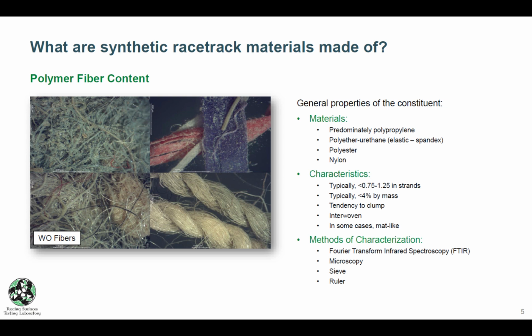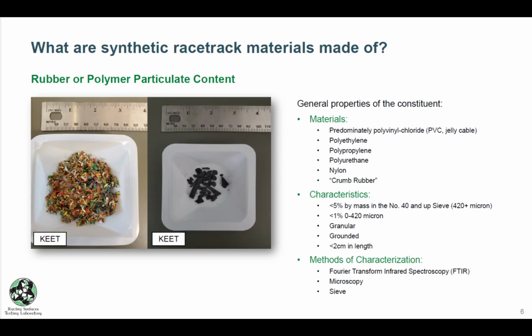I have seen with the newer Tapeta 10 that the fiber lengths are generally a lot more variable and they have a tendency to clump up. In some cases, it can even be mat-like. But again, we can test for these. We can figure out what they are and how much of the fiber content is present in the surface.